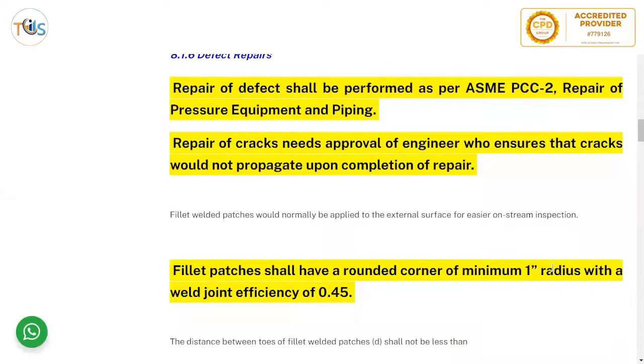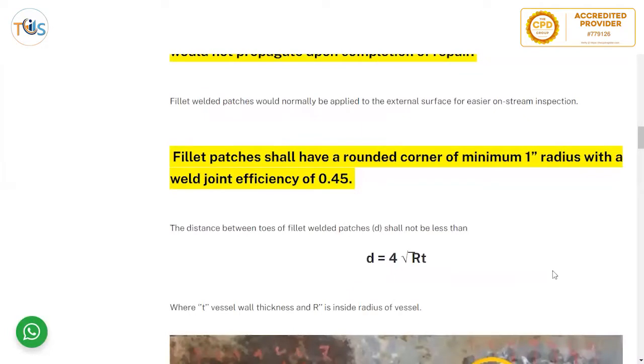Repair of defects shall be performed as per ASME PCC-2, repair of pressure equipment and piping. Repair of cracks need approval of the engineer who ensures that cracks would not propagate upon completion of repair. So if you want to repair a crack, normally you drill a hole at the tip of the crack to reduce the stress concentration, to reduce the sharpness of the crack, and then you normally remove the crack by grinding it off, and then build up by weldment. But then the engineers need to be involved to make sure that the crack does not propagate after you completed the repair. Fillet welded patches would normally be applied to the external surface for easier on-stream inspection.